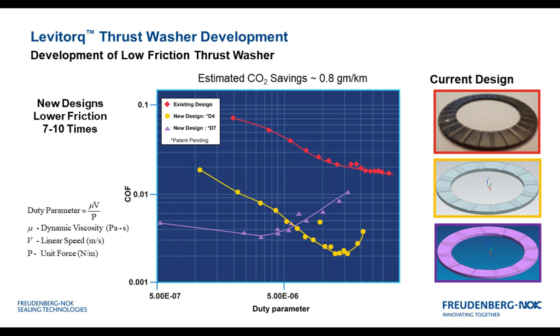And you can see that actually in the yellow curve there, an example of one of our patent pending designs where we lower the friction. We reach a low point where we're at the optimum where we're running without parts touching on a fluid film. And then we start to generate an increase in friction as we shear the fluid, and that creates additional friction. But we can optimize using designs to do so. In the example you see here, the yellow product, which is our D4 design, is one design we've used to lower friction and are in production today, which helps these products save energy.